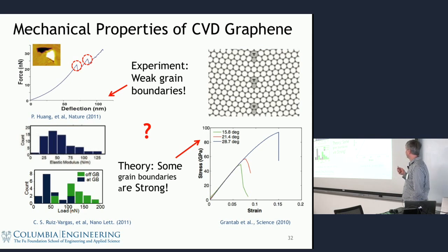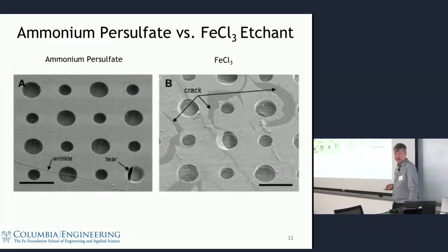On the other hand, there was some theory, this is one paper from Ruoff and Shenoy, that predicted that grain boundaries should be very strong. So what's going on here? Maybe a factor of 2 weaker than the bulk material. Well, one thing we discovered is that how you prepared the sample was absolutely critical.